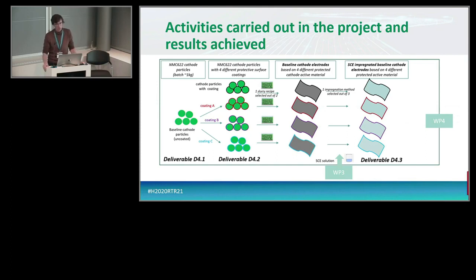Also there we have now selected one cathode that we are going to put into our cell. Basically here we start from an uncoated cathode material. In this phase of the project it was NMC 622. In a later phase of the project it will be NMC 811. But now NMC 622, non-coated, and then coatings were applied by different companies. Umicore took their standard coating. Delft EMP is a company that can put additional coatings on top of it by an ALD process. Different coatings were applied, and the goal of the coatings is to have a good interface between this active material and our solid electrolyte material. So these different coatings were put into cathode sheets. Cathode sheets were impregnated with the selected recipe for the solid electrolyte, the liquid precursors, and then solidified.